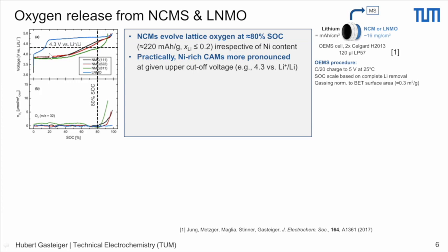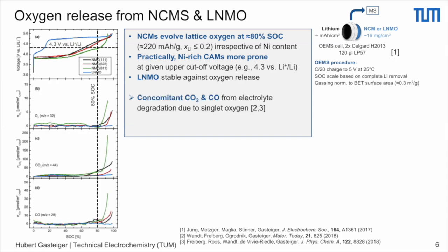When we look at potential, then of course what you see is that the oxygen release on the different materials occurs later for the nickel poor materials than for the nickel rich materials, right? So this has to do, of course, with the slightly lower voltage of the nickel rich materials. The LNMO, which here goes to as high potential as the NCMs, so about 5 volts, we see absolutely no oxygen, right? And so what we know is that the spinel structure is actually stable against the oxygen release. When we look at other gases, what we see is that whenever we have the onset of oxygen evolution, we also have the onset of CO and CO2 evolution, which we ascribe to the degradation of the electrolyte.